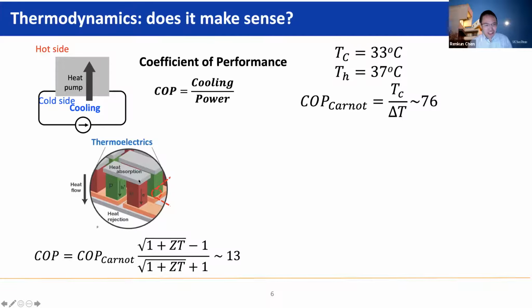So if we use thermoelectrics, there's a simplified equation to look at the COP of thermoelectrics, and it's a fraction of the Carnot COP. And this ratio is determined by this ZT, which is the figure of merit of thermoelectrics. Most commercially available thermoelectric devices or materials have ZT slightly lower than 1 or close to 1. So if you put in ZT of 1, you will get a COP on the order of 10. So this is more or less an idealized scenario using ZT of 1 with thermoelectric materials.